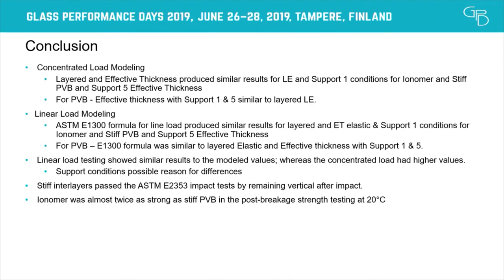So in conclusion, some of the things that we learned was that the layered and effective thickness produced similar results for the linear elastic and the support one conditions for the stiffer interlayers. The effective thickness for PVB and support one and five were similar to the layered elastic approach, linear elastic. For the line load, it was pretty good. The E1300 formula for the line load produced similar results to the layered and the elastic support conditions.